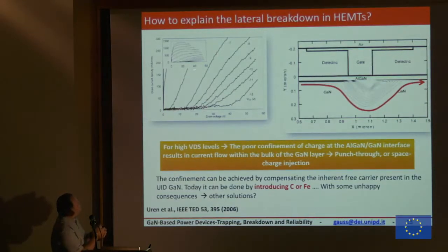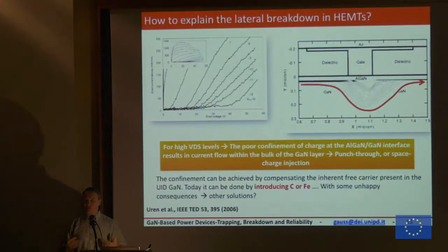And in order to close this current, you have to give more and more negative voltage to the gate. What is happening? This gallium nitride substrate is unintentionally doped. So it's grown without any intention to have any doping. But because of nature, maybe Elke spoke yesterday a bit, or he can help us to understand even more, during the growth, you do have some free carriers that came from impurities that enhance the carrier density. So this is not really intrinsic material. It is a little doped. So there is some conduction here.